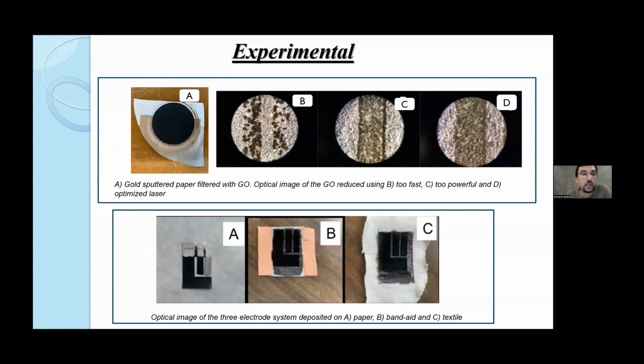Here, for example, in images B, C, and D, I show the morphological images of the electrode reduced using a too fast or a too powerful laser, and using the optimized parameters of the laser. As we can see, there is a different morphology because the laser parameters change.